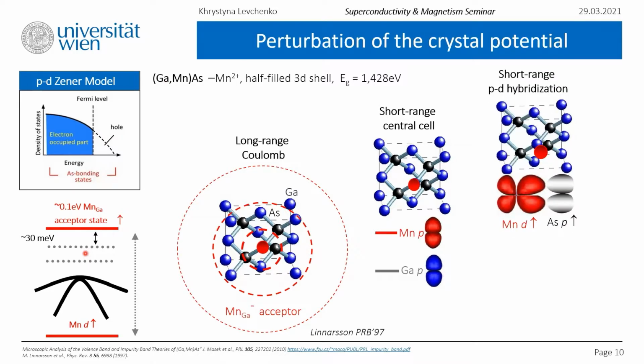And the last, remaining part of the manganese binding energy is due to the spin-dependent hybridization of the manganese d states with neighboring arsenic p states. And when we combine all three of them, we arrive at the experimental binding energy of around 0.1 electron volts. Again, binding energy is just the amount of energy required to separate a particle from a system. So this was with one manganese ion introduced into gallium arsenide.